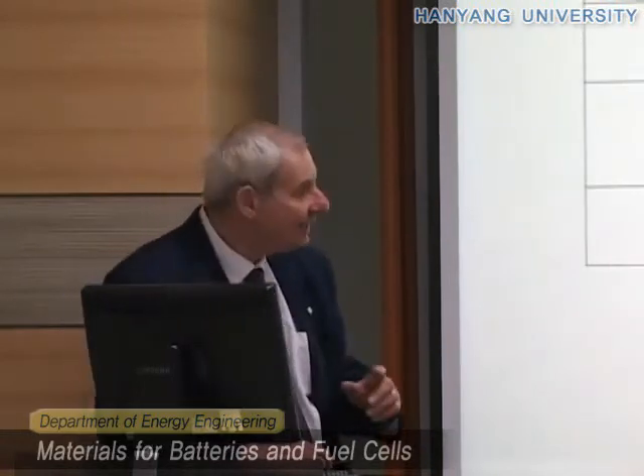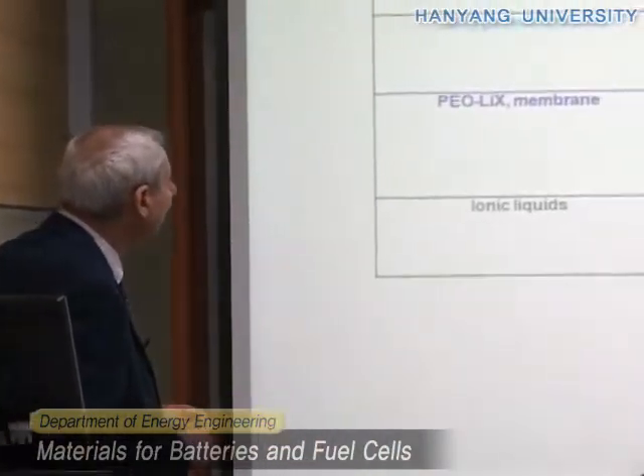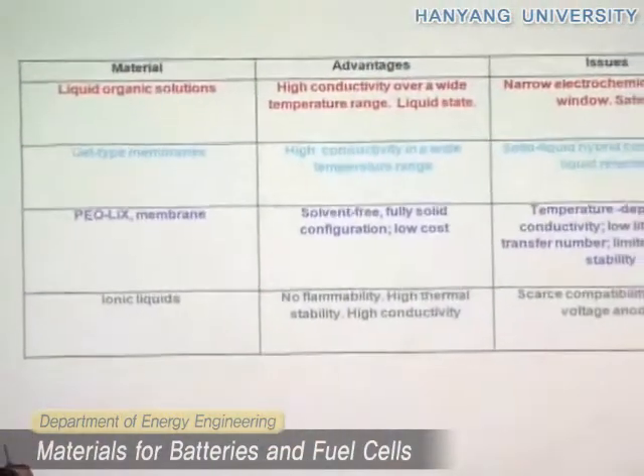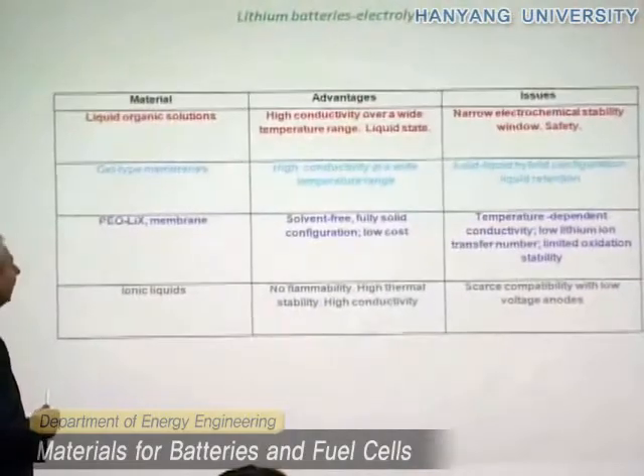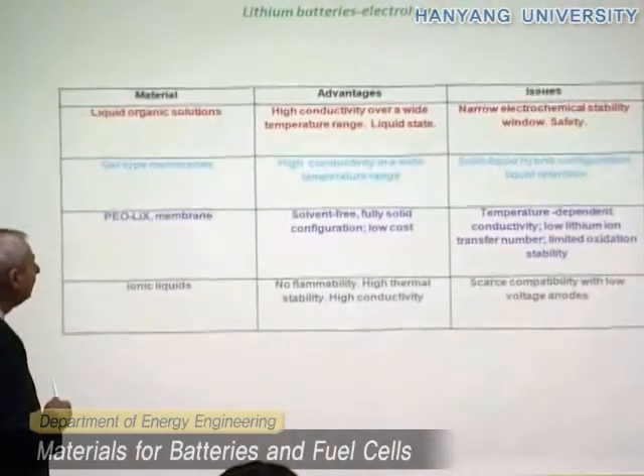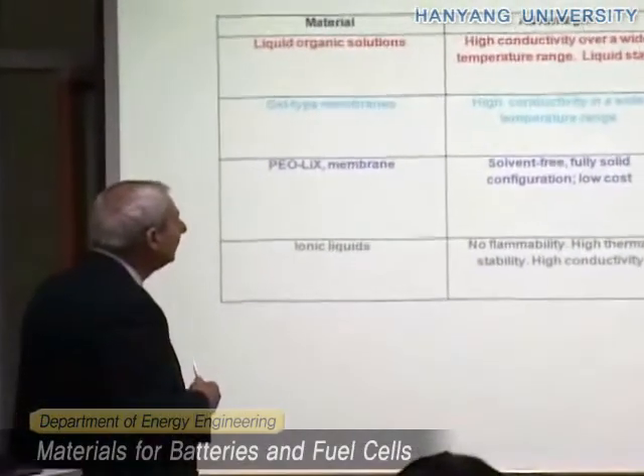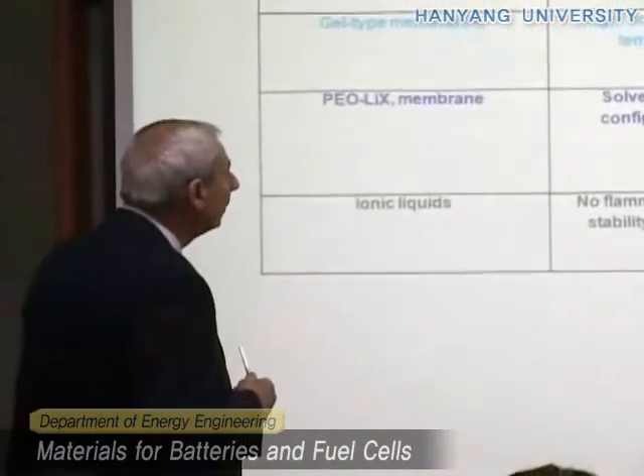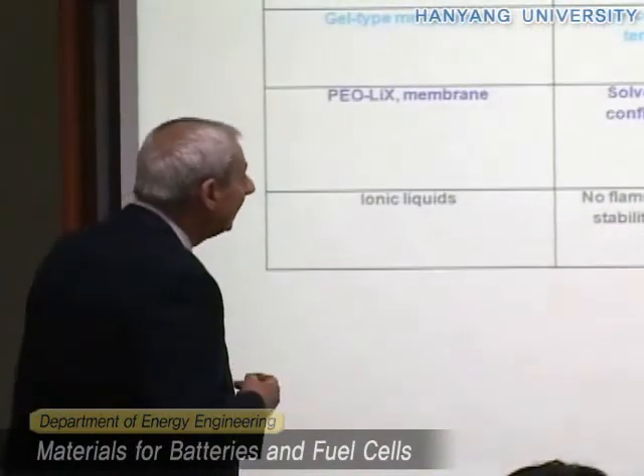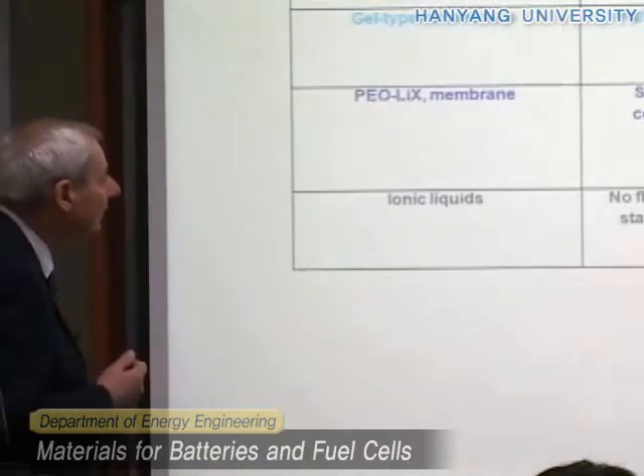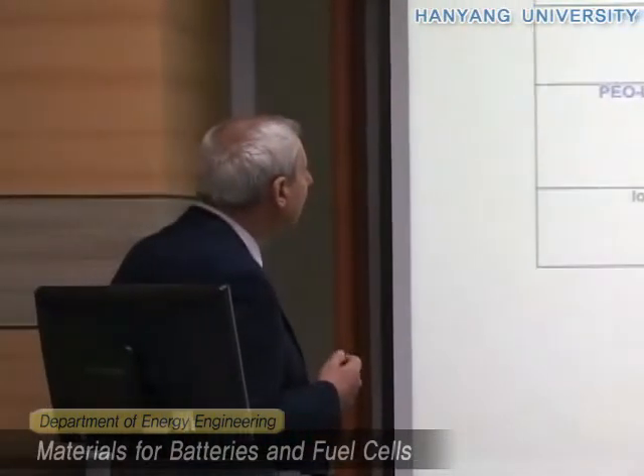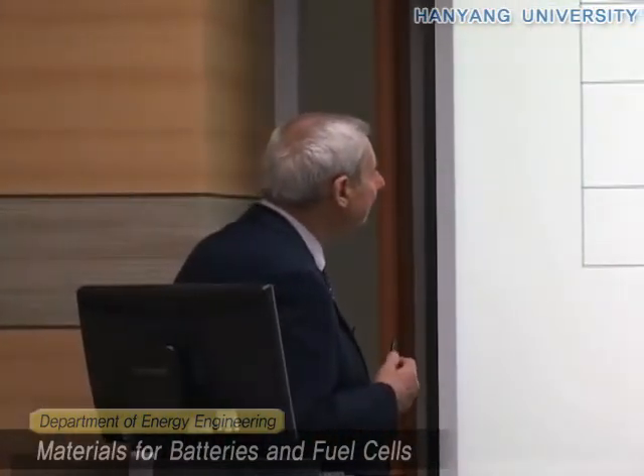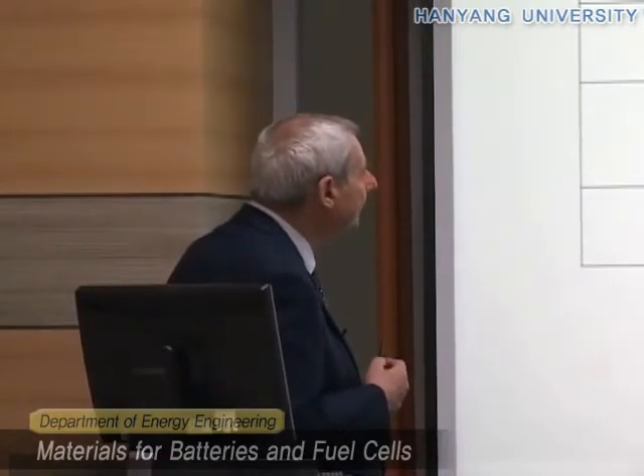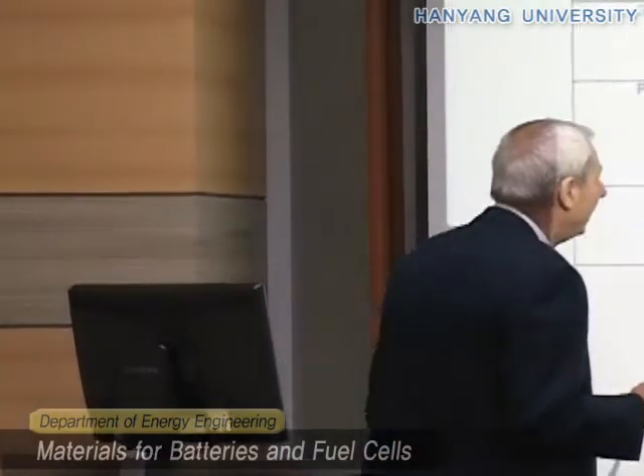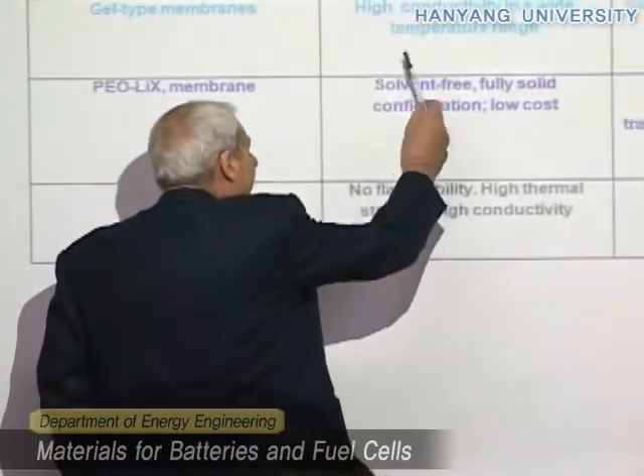Okay, let's summarize now the whole situation. You see, we start with the liquid organic solutions. Their advantage is high ionic conductivity, and the liquid state makes them easy to operate. But they have some problems with the stability window and safety. Gel-type membranes: the advantages are high conductivity in a wide temperature range, and I forgot to add here, of course, the plastic configuration.